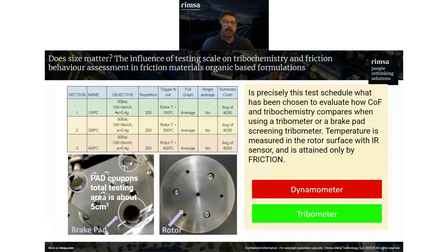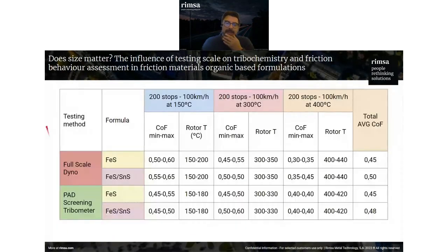and the tribochemistry evolves both in the dynamometer and the tribometer. So basically, this is a summary of what we have gotten in the four tests. We have the full-scale dyno, and we have the pad screening tribometer, in this case the MTF 5000. In the full-scale dyno, we have tested the formula with iron sulfide and the formula with iron and tin sulfide. And in the pad screening tribometer, we have done the same. And we have tested at 150 degrees, 300 degrees, 400 degrees. So we measure basically the coefficient of friction and the temperature we have achieved at each temperature.